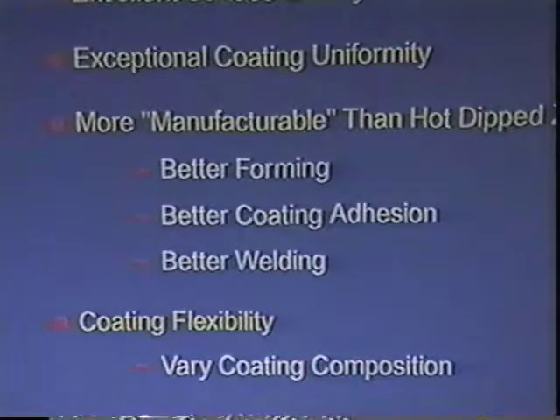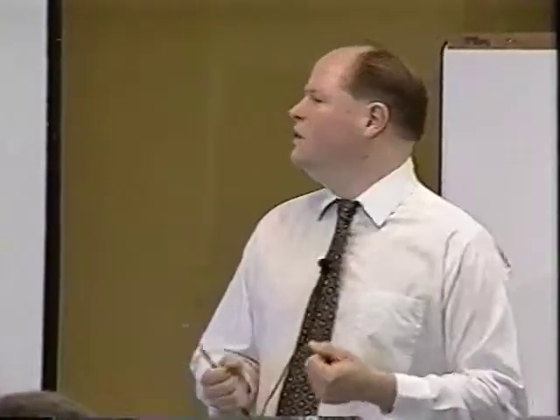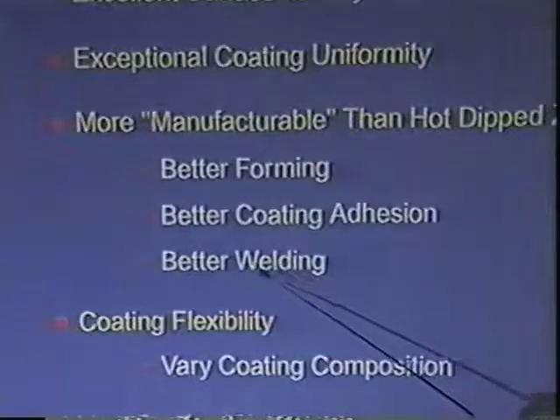We talked about galvanneal and the powdering problems. If you over galvanneal it, electrogalvanized, basically it's not going to come off. It's electroplated on. It's not going to come off. You bend it and form it. However, in galvanized, the coating's not going to come off either for the most part, unless you're really deforming it. But you can break galvanized and not have the coating fall off. So between EG and galvanized, pretty similar adhesions. Galvanneal definitely worse.